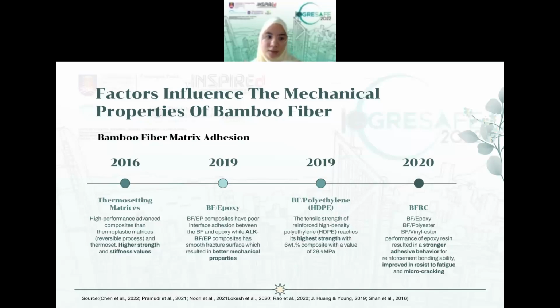So we can see that in 2016, there was a thermosetting matrix, which produces high strength and stiffness values. For bamboo fiber reinforced epoxy, as I mentioned earlier, when the bamboo fiber is treated in alkali, it has a smooth fracture surface, which results in better mechanical properties. Bamboo reinforced polyethylene showed that it reached the highest strengths. And bamboo reinforced composite epoxy polyester vinyl ester resulted in stronger adhesive behavior, which improved resistance to fatigue and micro cracking.